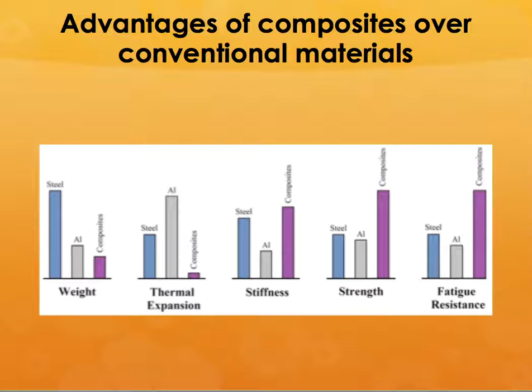We already talked a little bit about this, but if you really compare from a weight standpoint, see the difference. I mean, steel is about 7 to 8 times the weight of composites, and aluminum is almost double. But since the strength of composites is much higher than aluminum, the weight savings is probably more like 60 to 70%. Thermal expansion also, composites are much lower in thermal expansion.